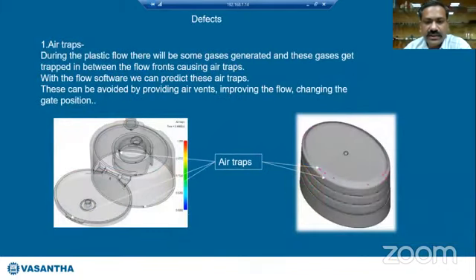And this one is about the defects. What are the main defects we are going to get on a plastic part? During flow, some gases are generated and these gases get trapped between flow fronts, causing air traps. With the flow software, we can predict these air traps. These can be avoided by providing air vents, improving the flow, and changing the gate positions. These are the main areas we need to look into to avoid air traps on the product.